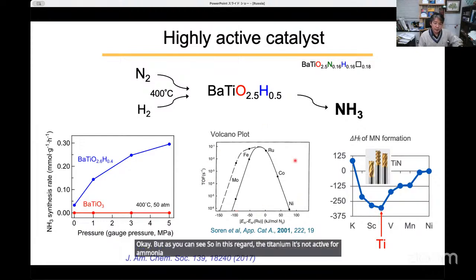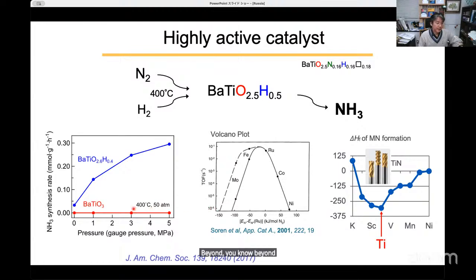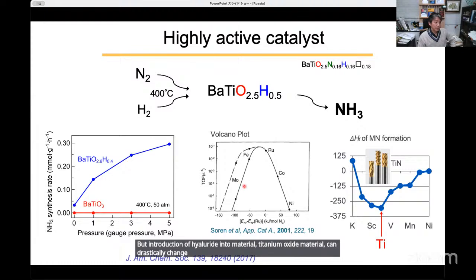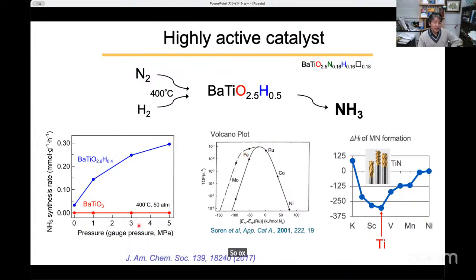So actually, in this volcano plot for nitride formation, titanium is located far beyond this graph, somewhere here. But introduction of hydride into a titanium oxide material can drastically change the scaling rules for catalytic activities. So I think this is a very nice example that the introduction of a non-oxide anion, or mixed anion, can drastically change and generate properties. Oxide cannot, in this case, be the catalyst for ammonia synthesis, but oxyhydride can do this.